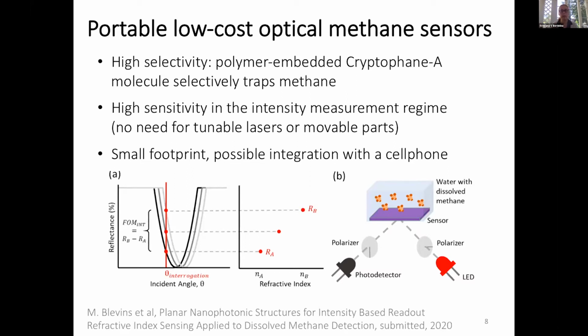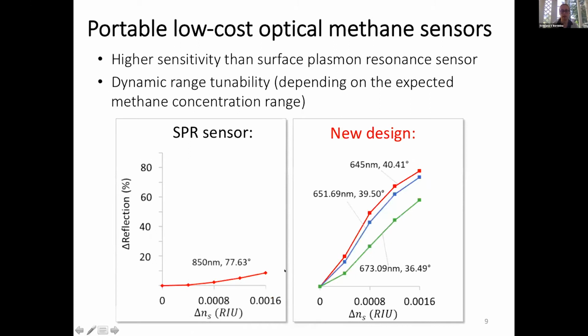And the detection is done by simply looking at the changes in the reflectance, the intensity of the reflected signal that is measured by the detector and comes from the LED, when some molecules of methane get embedded in the polymer matrix. And when that happened, we measure the shift in reflectance. And the shift that we have with our design, as you can see on this plot, is significantly better than the only other, as we know, more or less portable commercial sensor, which is based on surface plasmon resonance. So you can see that if you want to have a sensitive detector, you want the slope to be as high as possible. So any change in the methane concentration should result in a large change in the intensity of the reflection signal. And this is what our sensor provides.